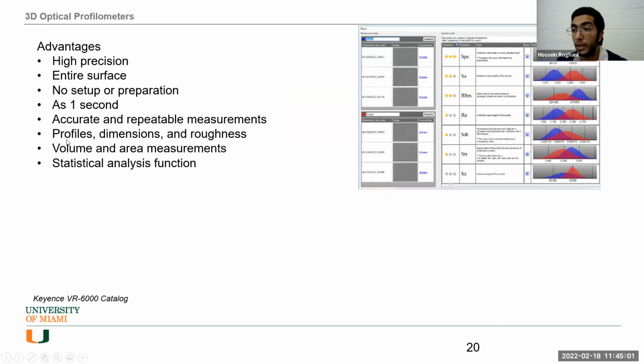And the volume and area measurements can help us also with the sand-coated rebars, because in the sand-coated rebars the roughness is important, and you should also have an idea of your particle size, because you should know the maximum and minimum sand particles on the rebars. Unfortunately, we cannot get those sand particle limits from the manufacturer, because it's kind of a secret for them.